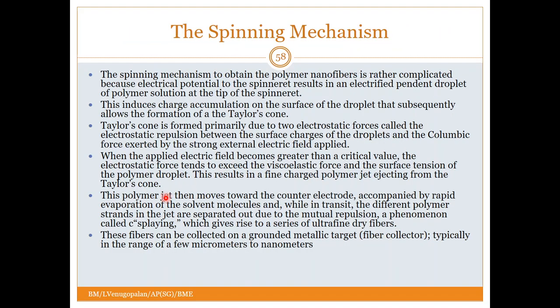The spinning mechanism to obtain the polymer nanofibers is rather complicated. Although this method looks fairly straightforward, the spinning mechanism is quite complicated because the electrode potential at the spinner results in an electrified pendant droplet at the tip of the spinner. This pendant droplet results in the formation of the Taylor's cone, the tapered end at the spinner. Taylor's cone is formed primarily due to two electrostatic forces: the electrostatic repulsion between the surface charges of the droplets and the Coulombic force exerted by the strong external electrical field. These two forces result in the formation of the cone. It is not a physical part of the device. It's just the polymer material that forms that cone and finally comes down as fiber.